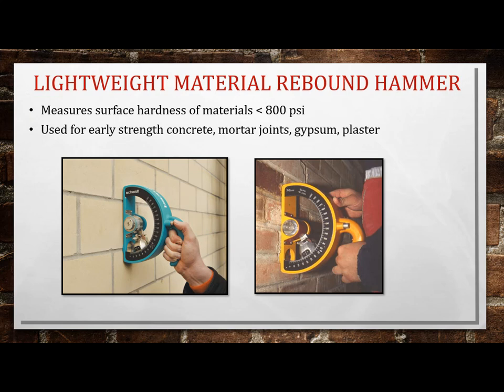So here's an example of a lightweight rebound hammer. This is for materials under 800 PSI. And you can do early strength concrete, like maturity testing, to determine mortar joints, gypsum, plaster, lightweight material.